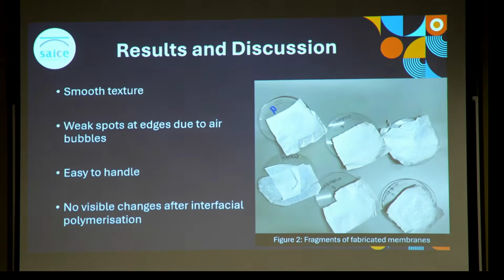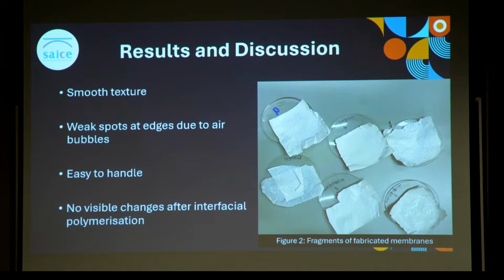After membrane fabrication, several notable observations were made. Firstly, the membranes exhibited a smooth surface texture, which is a desirable quality as it suggests uniformity during the fabrication process. However, as can be seen in the image alongside, weak spots were observed along the edges of the membranes, likely attributed to the formation of air bubbles during the fabrication process.